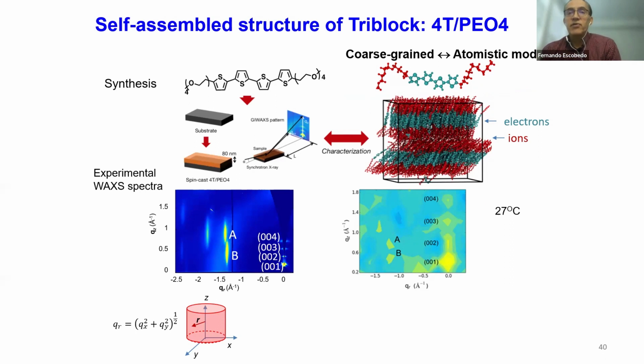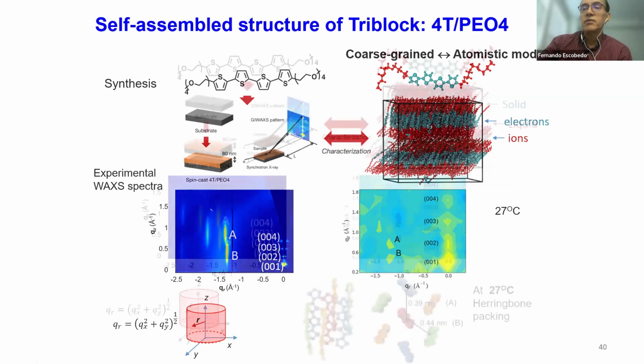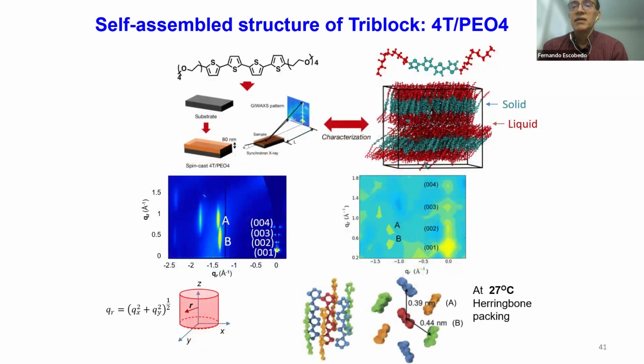So once you have the structure, of course, you can also analyze it using a simulated X-ray pattern. And then you can compare the experimental with the simulation patterns to make sense of these diffraction peaks. For example, the diffraction peaks shown here as 001, 002, and so forth, they reflect basically the layering structure of the material that was expected. So we know it's some sort of lamellar phase. But some of the A and B peaks were a little bit more puzzling. The analysis showed that they correspond to some sort of periodic distance in the system, reflecting the packing of the thiophene cores in the material.